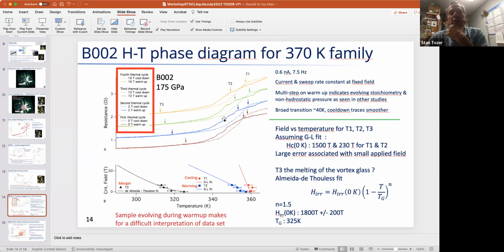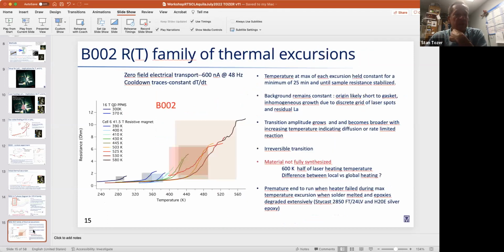There are fewer transitions in this warm-up trace, a smoother cool down, and here it's a little sloppier, admittedly, but the cool down is clean. And by the time we get up here, it's almost a clean transition, and the cool down is quite clean. So it's chemistry in action, or possibly electrochemistry in action at that point.